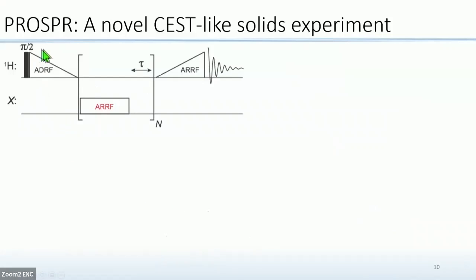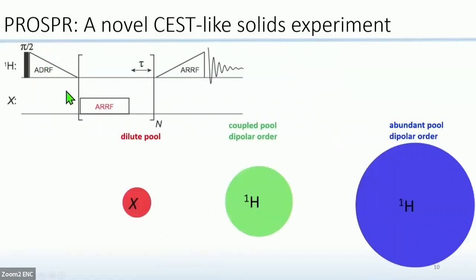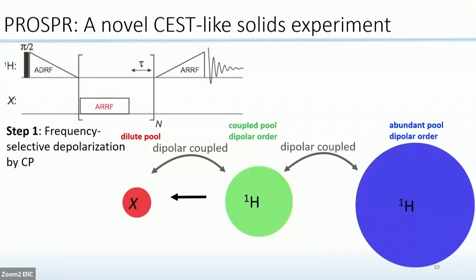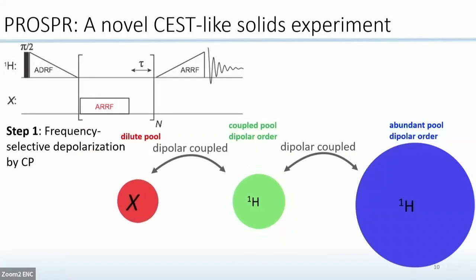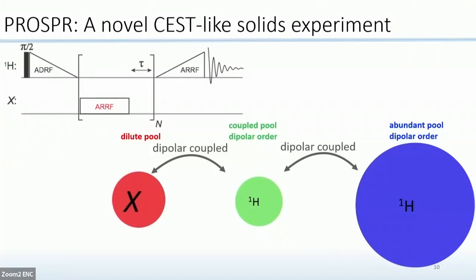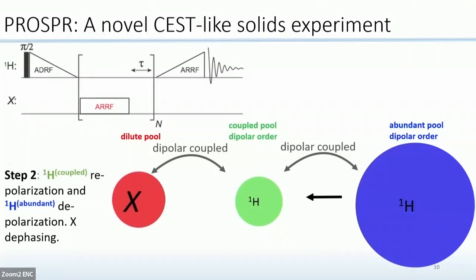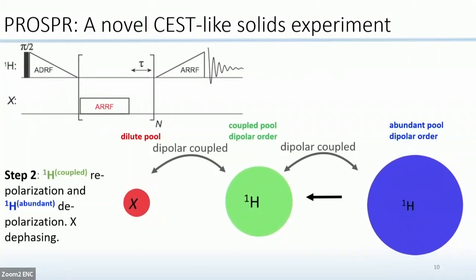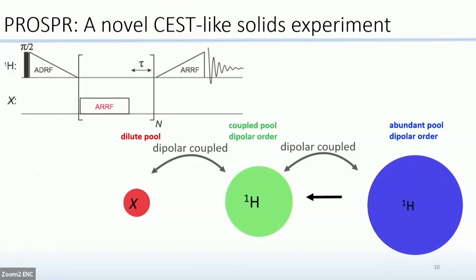And then following this ADRF, the generation of dipolar order, we have this type of loop CP. So I'll show here what happens in this type of loop CP. First of all, we have these X nuclei and these two distinct pools of protons. So we start by doing this frequency selective CP, and then we essentially deplete the dipolar order on the coupled pool. Then, at the same time, we have a delay here, tau. And during this delay, the dipolar order of the coupled pool is replenished by the abundant distant pool, and at the same time, the X magnetization dephases.